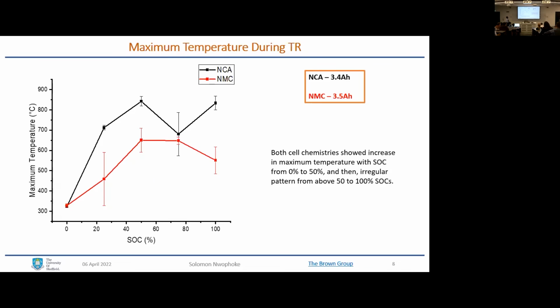Then the maximum temperature attained. The black plot shows the NCA, and the maximum temperature increased with state of charge up to 0.50, where the maximum temperature was already recorded, and then followed an irregular order to the rest. And the same thing happened for NMC. So this indicates that the amount of heat that can be released from a battery when it undergoes thermal runaway can be as much as it could be at 100. I don't know if you understand that. Like at 50% state of charge, a battery can really release a substantial amount of heat, as much as it could when it is charged to 75 or 80 or anything more.